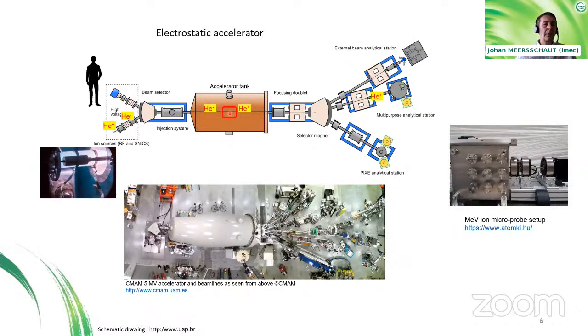So if you have 2 million volts in the center of the accelerator, the exiting helium particle will have an energy of 4 mega electron volt. One of the advantages of such a system is that by stabilizing the accelerating voltage to about 1 kilovolt, you can achieve very narrowly defined energies for the exiting particles that are emitted from the accelerator. And this is why such an electrostatic accelerator can be used to energy dispersively measure the interaction of the particles